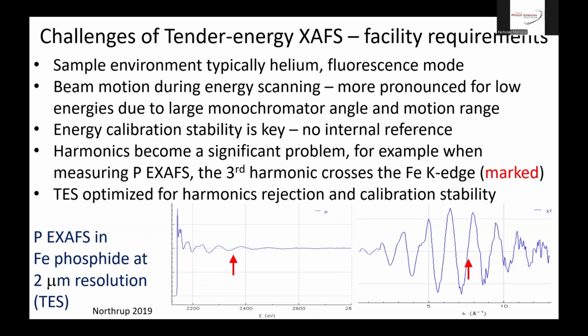So some of the challenges for the tender energy XAFS, you start with the facility requirements, what it takes to be able to do this in the first place. The sample environment is typically helium. Many samples are not vacuum compatible, so the atmosphere of choice is helium. About this much air will absorb your beam, so you need to have something more transparent around your sample, but that limits your sample somewhat.